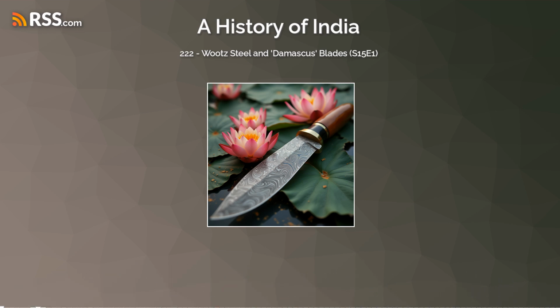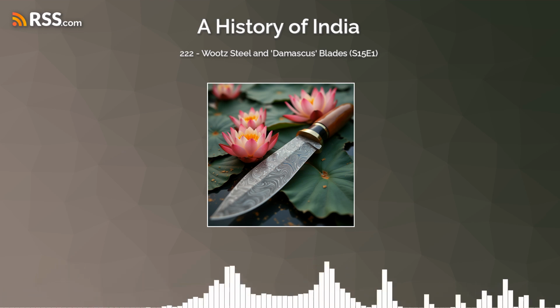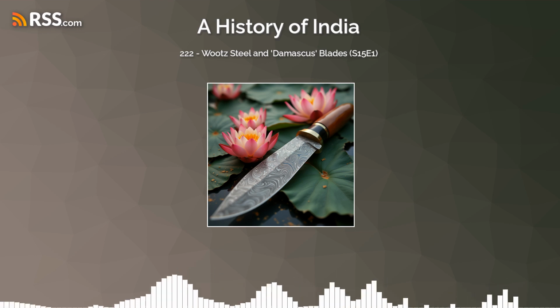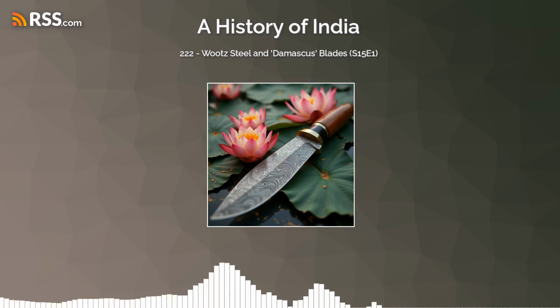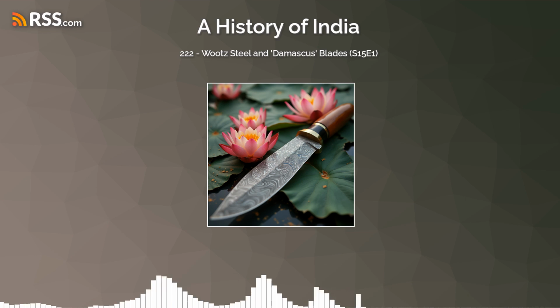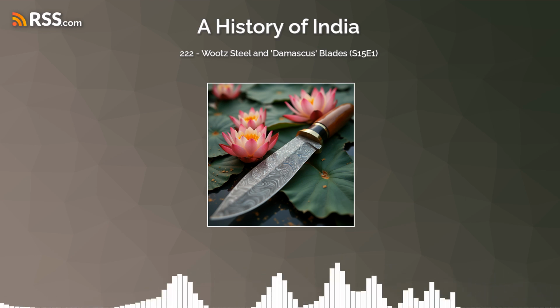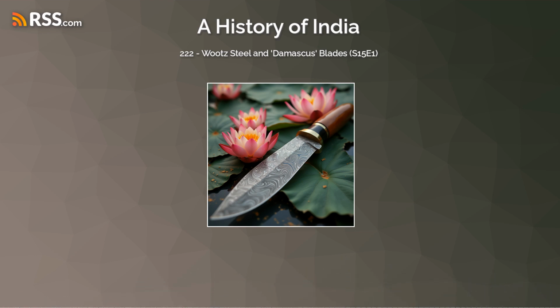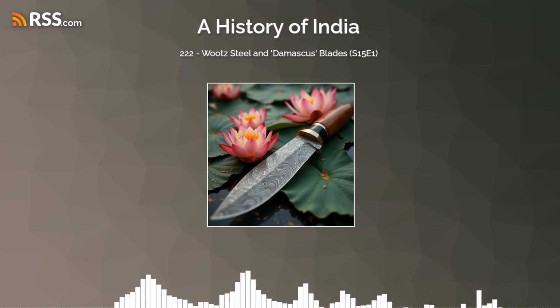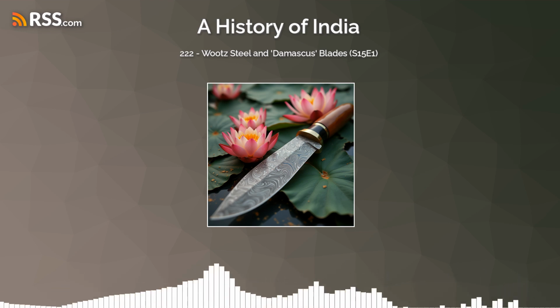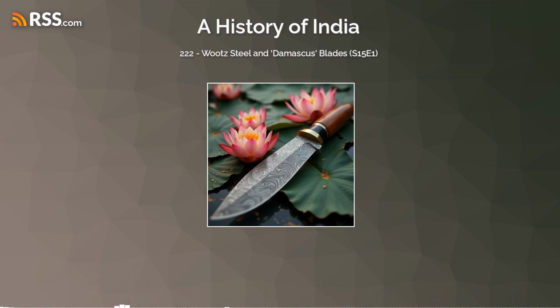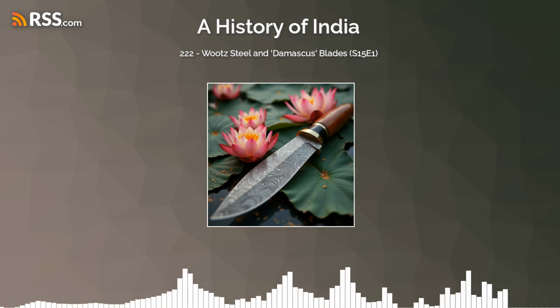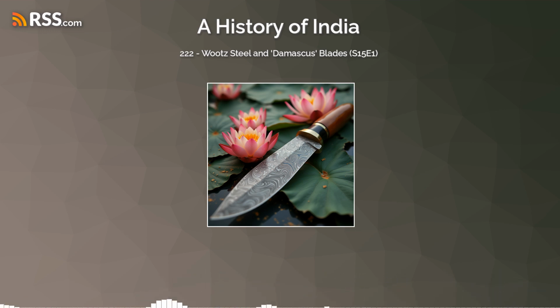And the heating itself. These crucibles went into special furnaces. Right. The sources, especially some Arabic ones, mention furnaces, sometimes called kur. These had to be capable of reaching and holding very high temperatures, probably at least 1250 degrees Celsius, maybe even higher. And for long periods, firing cycles of around 24 hours are often mentioned. Why so hot? Doesn't iron melt lower than that? Regular cast iron does, yes. But this specific ultra-high carbon steel needed those higher temperatures to fully form and homogenize within the crucible.